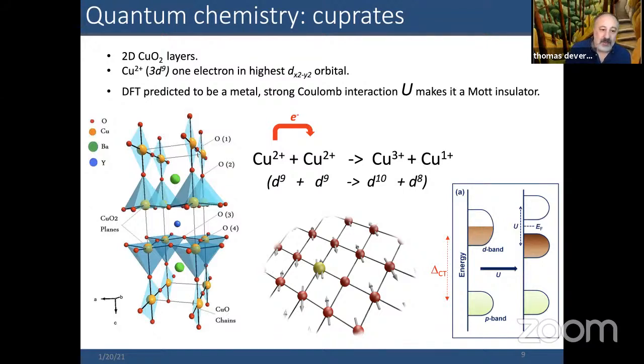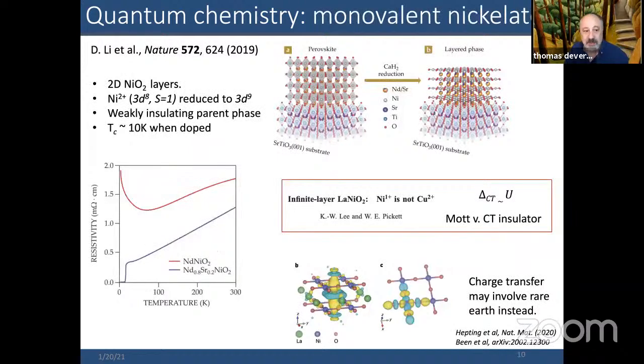an aside, to think about the monovalent nickelates, where the nominally nickel 2 plus can be reduced so that instead of being a 3d8 spin-1 system as it is in most nickelates, by this topotactic reduction it turns out to be mostly d9. So we would think it would be more akin to the physics of the cuprates, and that's why it was very exciting that when doped off of its weakly insulating parent phase, superconductivity was recently found with strontium doping on the order of 10 percent, with the Tc on the order of 10 Kelvin or so.